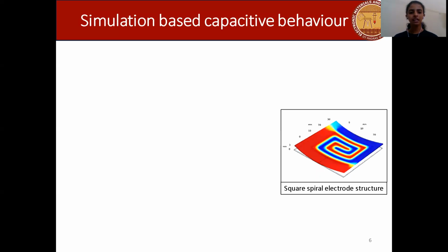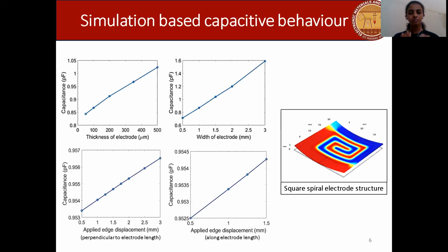In case of a square spiral electrode structure, I have observed that similar to the interdigitated comb-like structure, the capacitance value was increasing with electrode dimensions, and with edge displacement, here in both the cases, that is the axis being along the electrodes and perpendicular to the electrodes, the capacitance value was observed to increase, which means we can observe a net reduction in the electrode gap. While in this case, the overall plane state capacitance values are almost 1/3 of the initial interdigitated comb-like structure. Here the capacitance ranges are from 0.8 to 1.5 picofarad.